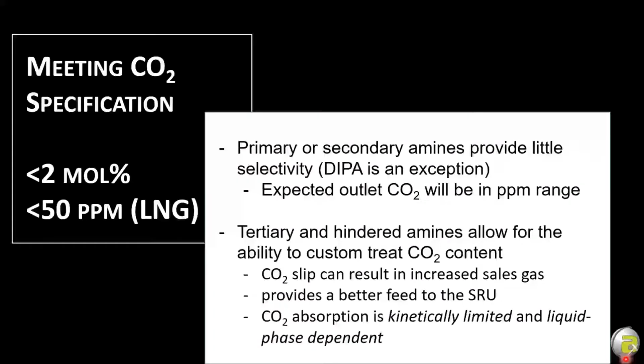For CO2 spec, typically pipeline spec is less than 2 mol%. If you're feeding gas to an LNG facility, we need the CO2 down to less than 50 ppm, and the reason for that is CO2 freezes in the cold parts of that facility when we're liquefying the natural gas. So we need to keep CO2 out. CO2 needs cool amine, it needs good contact, it needs a well-regenerated solution, but also remember that the different types of amine react differently with CO2.